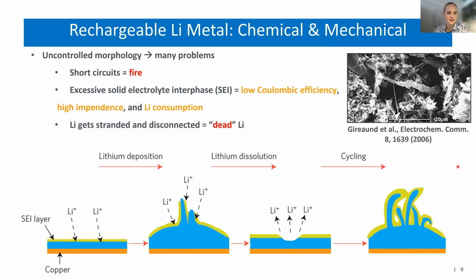Why it doesn't work well is because it has an uncontrolled morphology. So lithium likes to form these high aspect ratio grains, which are not good because they will increase the interaction between the lithium metal and the electrolyte, which will then grow what's known as the solid electrolyte interface layer, which is this lighter green color on top of the blue. And then as you cycle, it continues to grow and develop. As you strip the lithium away, you can strip either from the tip or from the base. If you strip from the base, then you can be left with a lot of dead lithium that no longer contributes to your capacity inside your battery. And so we see lithium consumption both from dead lithium, but also from reaction with the electrolyte. And so we are trying to understand how to better control that lithium morphology.